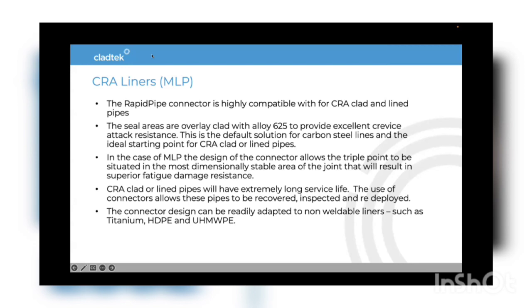And as I've mentioned several times before, particularly adaptable for non-weldable liners like titanium, HDPE, ultra-high molecular weight polyethylene. Particularly the latter two we see in seawater injection, and we also see interest in these kinds of liners for mining applications. So deep sea mining, where a slurry has to be pulled up through a riser, those sort of wear resistant non-metallics are of interest, and connectors really lend themselves to dealing with those.